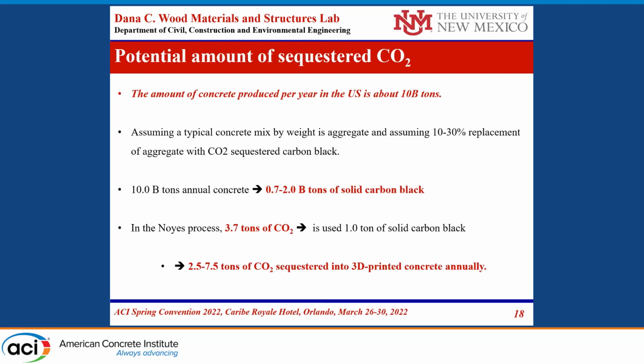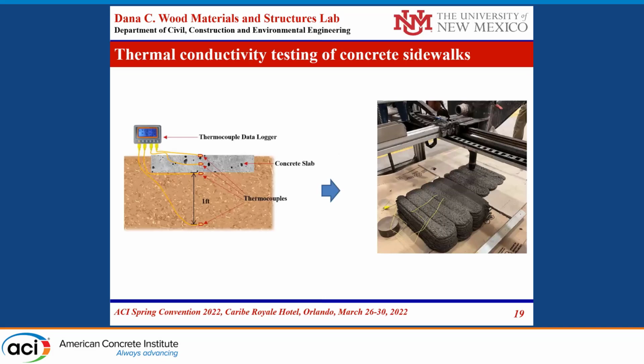The manufacturer of this carbon black tells us that they use about 3.7 tons of CO2 to produce 1 ton of the solid carbon black. That would translate to this: for the 10 billion tons of concrete, we can actually use on average about 5 billion tons of CO2 in this CO2 sequestered carbon black, producing concretes, again, in the typical strength range between 3,000 and 4,000 PSI, and being 3D printable. So this is, again, our 3D printing.